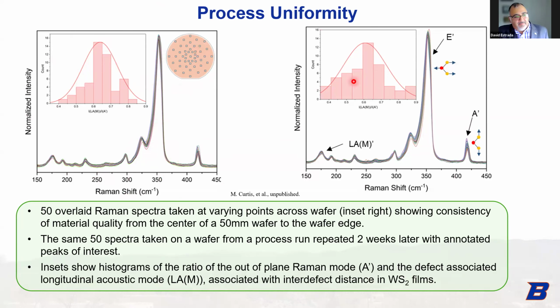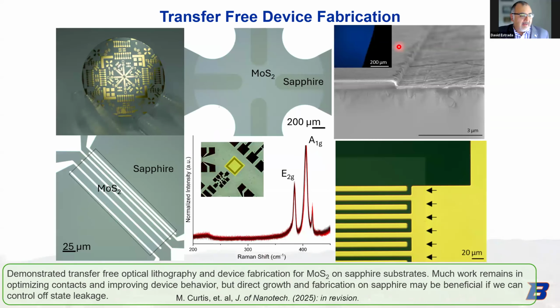And then this is the same Raman scheme, but done on a process that was run 2 weeks later. We do see a bit of a spread in the ratio of the LA mode to, I think, the A prime mode, which is an indicator of defect density. But overall, the process looks pretty uniform, even weeks apart. The recipe is pretty constant. We're still improving our growth recipe, trying to get lower monolayer coverage.